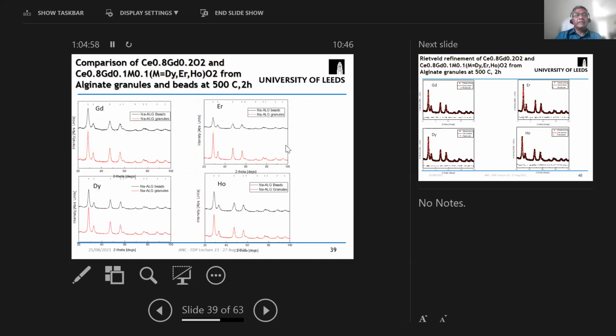And to our surprise, it doesn't make any difference. This is pure CGO, cerium gadolinium oxide, calcined, produced using sodium alginate beads and using sodium alginate granules. This is the bead process. The red trace is from the granule process. So granulation also yields identical purity and crystal structure for various compositions. So we are now researching using granules as well, along with the beads, to produce the functional nanomaterials, oxide nanopowders.